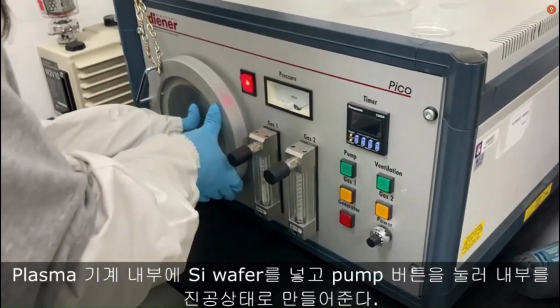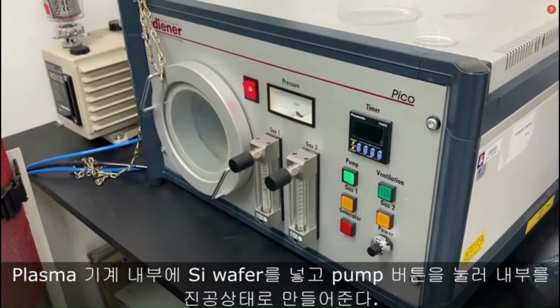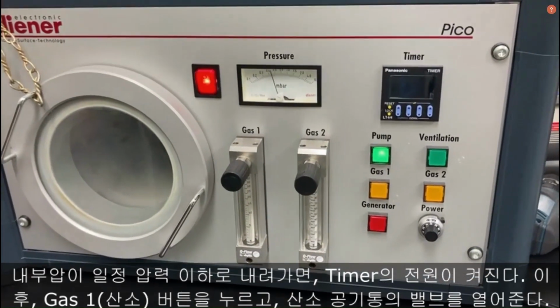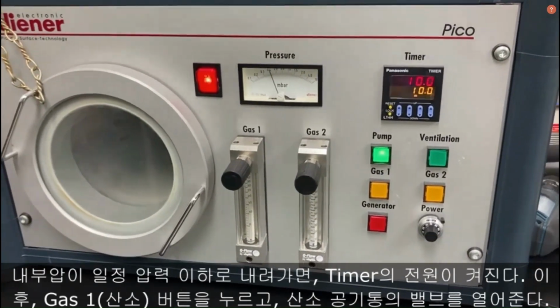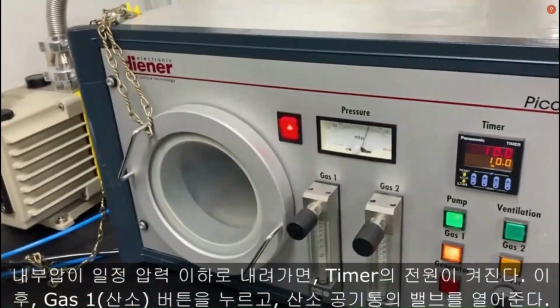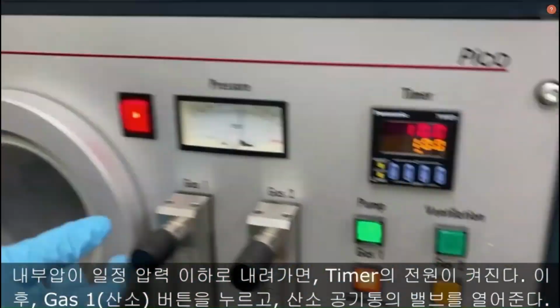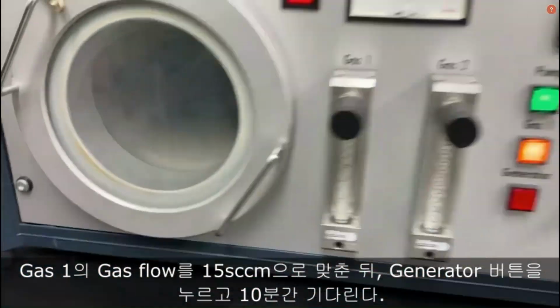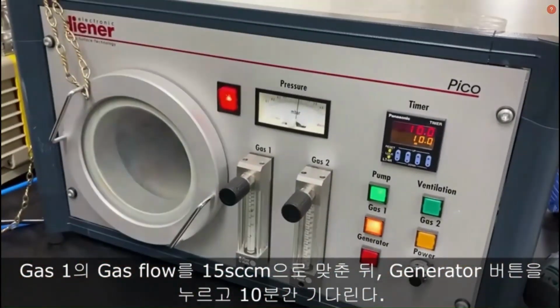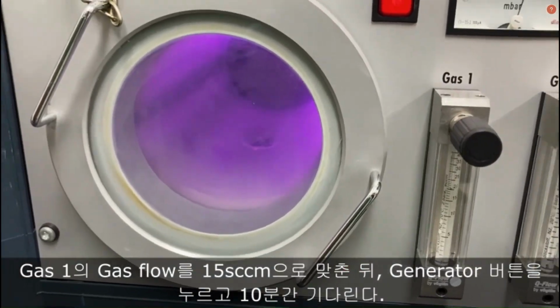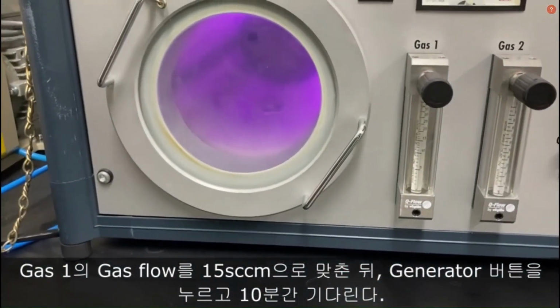Put the wafers into the plasma machine. Then press the pump button to make a vacuum. You can see the timer turns on when the pressure becomes lower than the threshold pressure. Then press the gas 1 button and open the oxygen gas valve. Adjust the gas flow to 15 sccm, then press the generator button and wait for 10 minutes.